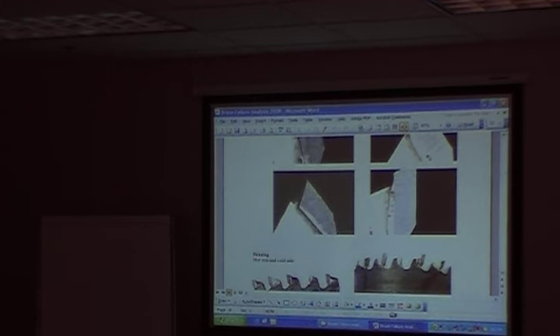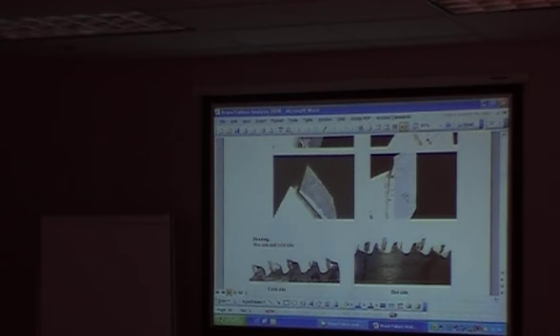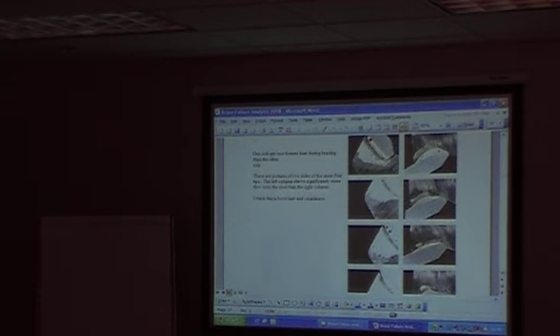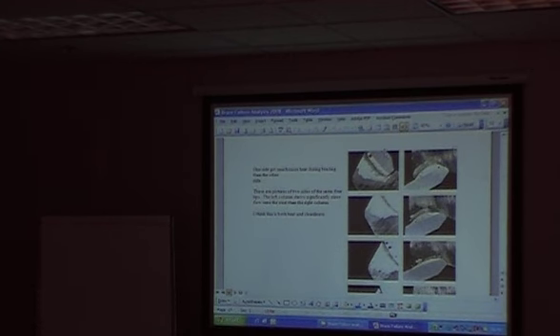Those are hemispherical. That's indicative of overheating. When you overheat, the zinc forms bubbles. So this braze alloy got too hot. This is probably okay, but only marginally so. Here you can see the flow back onto the plate. The steel's clean because that's a good flow back onto the plate. Much better than over here where you don't have the wetting onto the plate. You have a huge zinc bubble up here, which is not good.